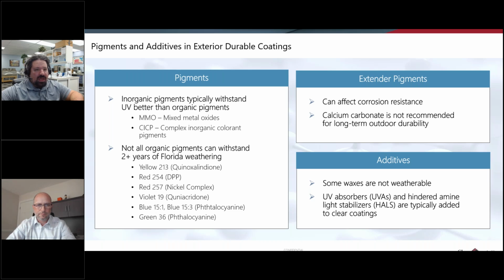But waxes are used in powder coating sometimes to have an effect on the surface, and so we put in a wax, it melts in the curing phase, and the waxes typically come to the surface, and that's why they're used for slip resistance, additional scratch and mar properties. They can even be used to adjust the gloss. But since the wax has come to the top, if you use a non-weatherable wax, then it's going to very obviously be affected by UV exposure.